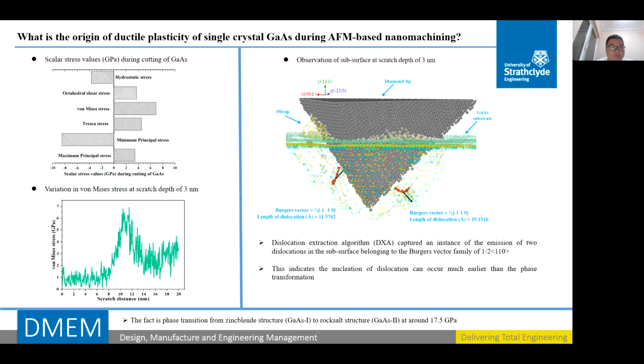On this page, it's well known that the Mises stress and the von Mises criterion can be used to predict yielding in ductile material. By contrast, the principal stress criterion is more suitable to predict yielding in brittle material. Single crystal gallium arsenide is hard and brittle at room temperature, but its chip can be removed through ductile mode. Therefore, this research looked into stress tensors and yield criteria that can be applied to describe plasticity in gallium arsenide. To achieve this aim, scalar stress values were obtained in the cutting zone.